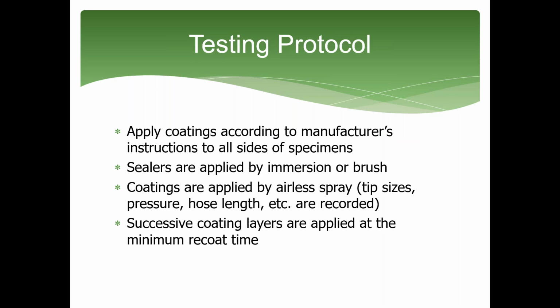All of the coatings are applied according to the manufacturer's instructions. Coatings are applied to all surfaces of the specimens. Sealers are applied by either immersion or brush application. Coatings are applied by airless spray, and complete records of the coating application are kept. Parameters that are recorded include tip sizes, pressures, hose lengths, ambient conditions. All of those things are recorded on the application forms. And successive coating layers are applied at the minimum recoat time, and that recoat time is specified by the coating manufacturer.